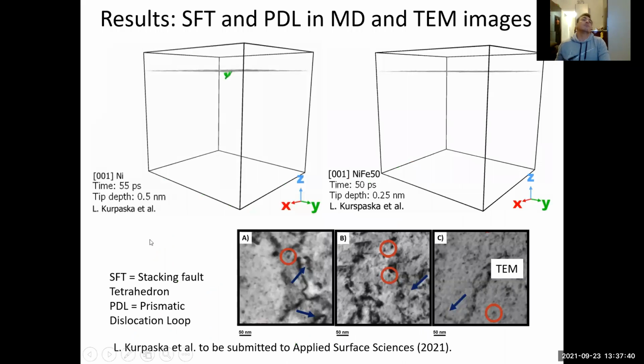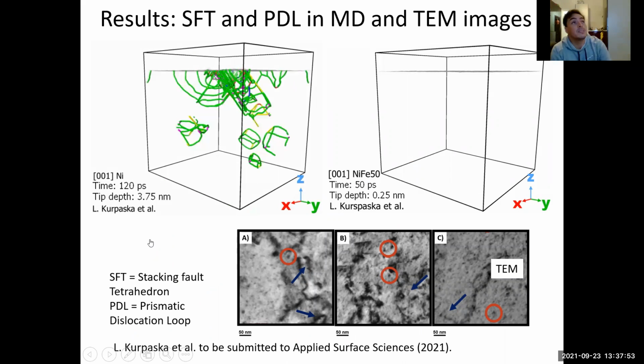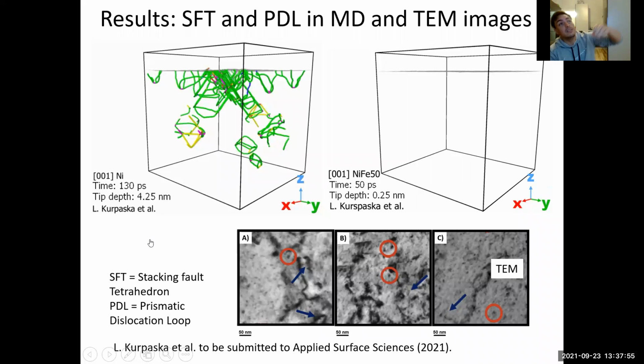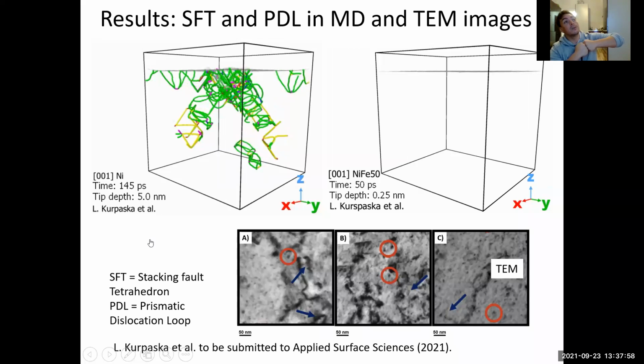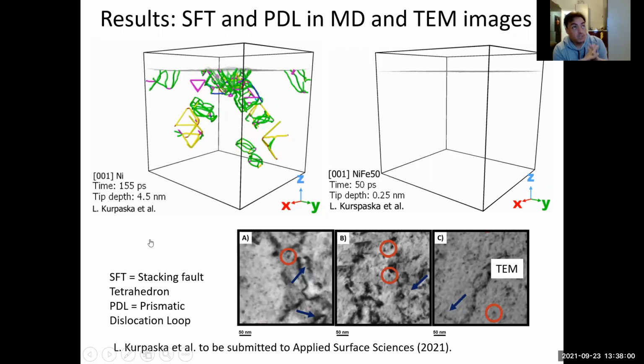This is the thing that I was talking about. You have the nucleation, then you have the slip system in the 111 slip system, and then because it's an FCC material, you have the nucleation of the prismatic dislocation loop, and then here you can see the interaction between the prismatic dislocation loops and then the formation of the stacking fault tetrahedron. This has the Hirth junctions, these yellow lines. Then you also can see here this triangle that is the stacking fault tetrahedron. And then here you can see the tip depth, and then the time of the simulation.